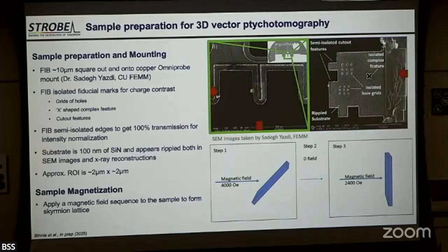And how thick is it? For your techniques, do you care how thick? Yes, we do care how thick, because the X-rays have to make it through. But it turns out skyrmion multilayers that support skyrmions need not be very thick, so it's fine to image in transmission. The X-rays can make it through. This is soft X-rays near the iron L edge, which is about 700 eV, 750 or something.